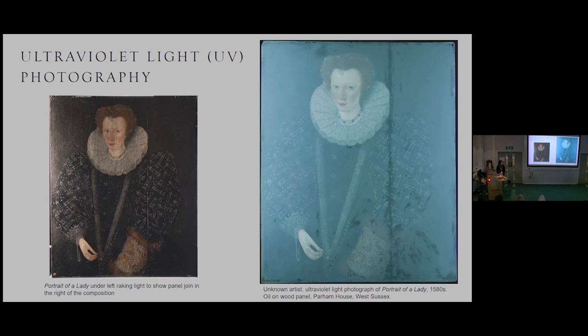The darker patches we do see are retouching that are covered by the varnish, as these would usually appear a dark purple color under UV light. We can see a concentration of retouching along the right panel joint. I've put a raking light image so we can clearly see the panel joint that it is covering coming through the front. Those we do see, however, only represent the more recent campaign of retouching, since the thick and aged varnish obscures the other overpaint present on this work.